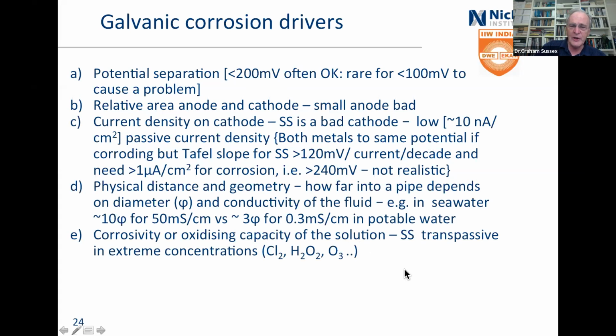Physical distance and geometry, so how far apart they are, can be quite important. Talking about pipes, it's going to depend on the diameter of the pipe and the conductivity of the fluid. So in seawater, you've got about 10 diameters for the 50 millisiemens per centimetre versus about 3 diameters for freshwater. Keep that in mind when you're putting in a separation or a sleeve down a tube on a heat exchanger, that it depends very much on what the conductivity of the material is, how far down you've got to shield, and the corrosivity or the oxidizing capacity of the solution.